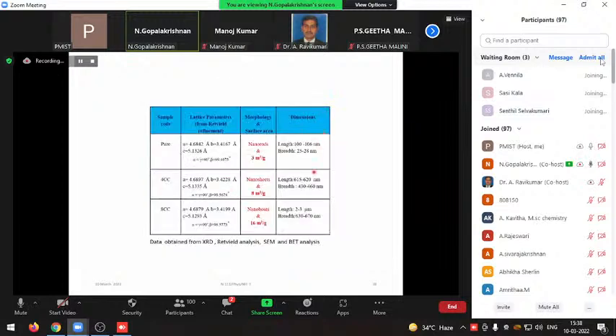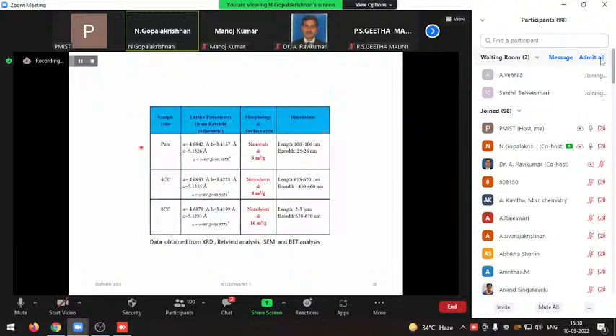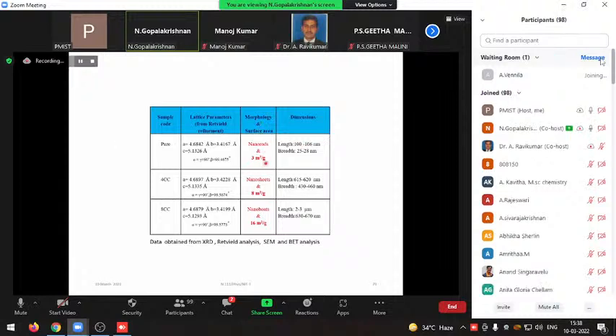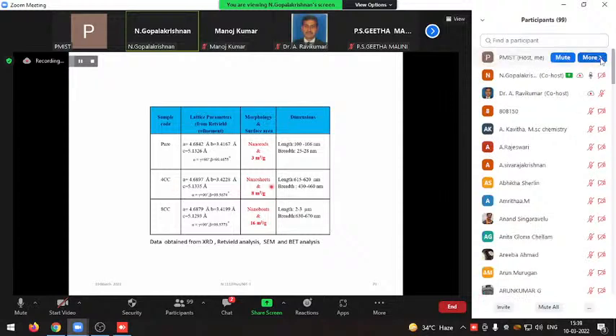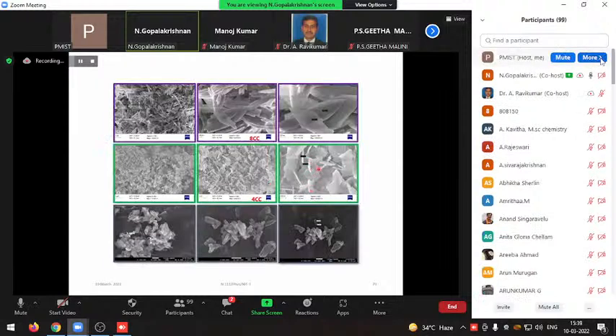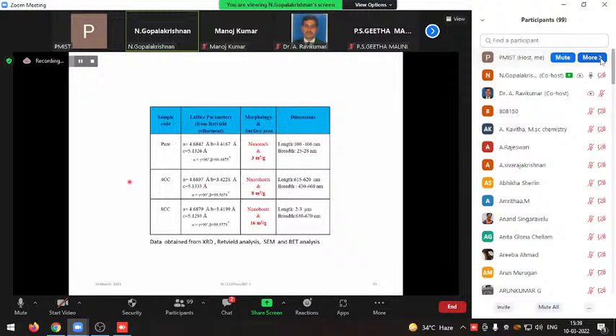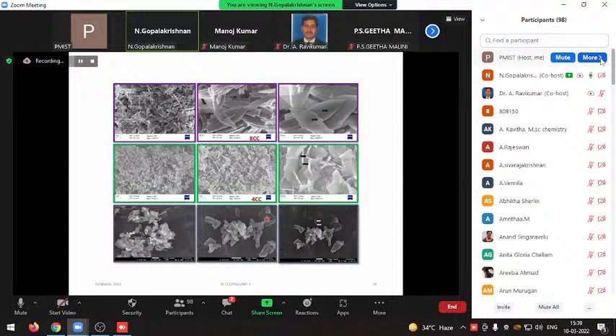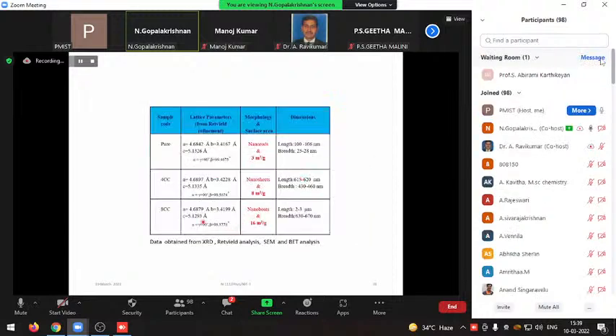Then this slide summarizes. In the pure case we get nano rods, and the surface area is only 3 m squared per g. In the second case, nano sheets, upon doping with chromium 4 atomic %, we got 8 m squared per g. And in the third case, the morphology is nano boards, 16 m squared per g. We give the dimensions here. That means we tune the morphology, and upon tuning the morphology we get a higher surface area.